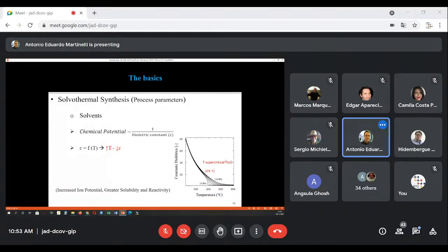For water, which you see here in this graphic, the increase in temperature results in a decrease in its dielectric constant. Below the supercritical water temperature, which is around 374 degrees Celsius, the dielectric constant does not show a significant dependence on pressure. However, above this temperature, the dielectric constant drops sharply at low pressures, around 230 bars, and decreases mostly at high pressures, 1 kilobar.